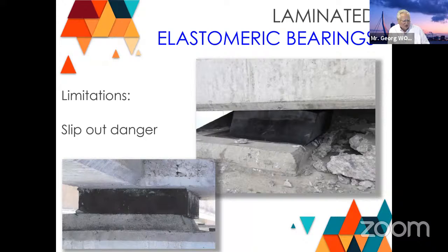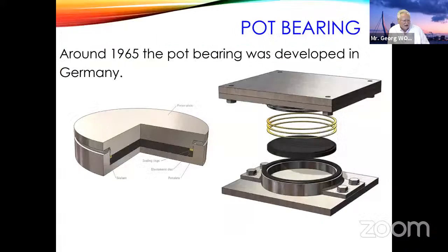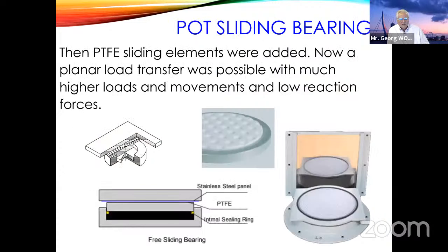This was, let's say, in the 60s, and then at the end of the 60s, 65, in Germany, the pot bearing was developed. The pot bearing is a steel pot with a rubber disc inside and with a seal here. So the rubber works like a fluid in a hydraulic cylinder, and you have a piston, and on top, shortly later, we got the PTFE sliding material, and in combination, you can make sliding bearings and guided bearings.